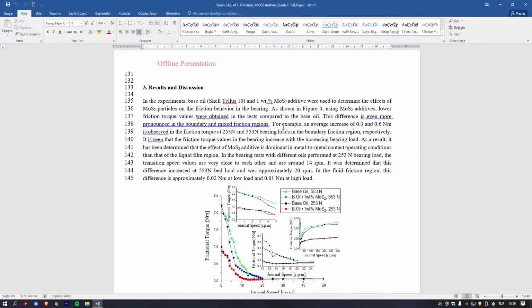For example, an average increase of 0.3 and 0.6 Newton meter is observed in the friction torque at 253 Newton and 553 Newton bearing loads in the boundary friction region respectively. It is seen that the friction torque values in the bearing increase with the increasing bearing load. As a result, it has been determined that the effect of molybdenum disulfide additives is dominant in the metal-to-metal contact operation conditions rather than in the liquid film regions.